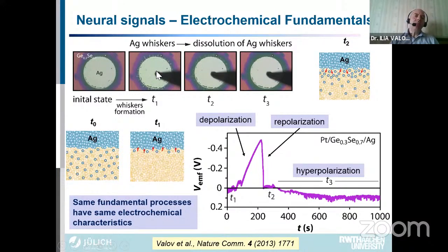Then we apply negative potential to the silver electrode, and you see after application of the potential, silver whiskers start to grow here. And you saw also the change in the morphology of the electrode, because you extract the dissolved ions, you extract them out of the material. And then exactly at this point, when the whiskers stop growing anymore, you switch the applied potential off, and you start measuring the voltage which is delivered by this cell. So this is like a battery. We call this nano battery. And you see what happens with the voltage which is generated by this cell. And at the same time, you see how silver whiskers start to dissolve back into the material.